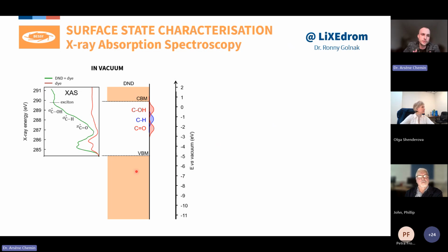So first thing first, we measure the X-ray absorption spectroscopy of the system. And you can see here the absorption spectrum. As I presented you before, you have a very large absorption corresponding to the conduction band of the diamond. And below it, you have many surface groups. So you have the COH here, the CH group here, the C=O here.